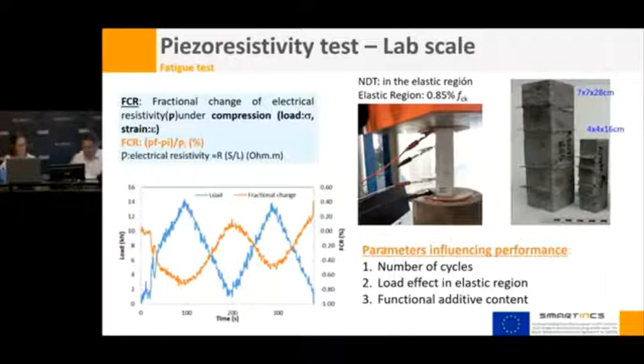A preliminary test was performed in an elastic resistance zone of this material. This zone was considered with an approximate value below 85% of the characteristic resistance of the material to be tested. And that was our reference.